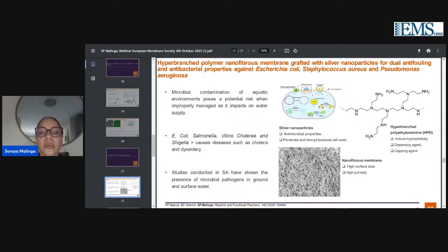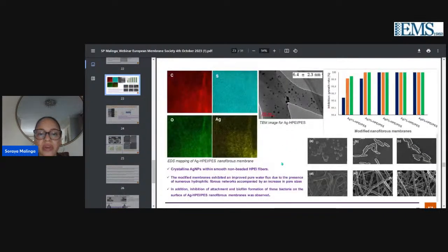So we spun that. A lot of optimization, as I said, in terms of controlling your size. We did quite a lot of optimization that normally takes about 6 months. Then we expose the membrane to UV light to reduce the silver salt to silver 0. We also prepared these within hyperbranched because obviously silver does aggregate. So it acted as a dispersing and capping agent. When we viewed this under the microscope, we could see that they're quite small and nicely dispersed, and the shape was sort of spheres.